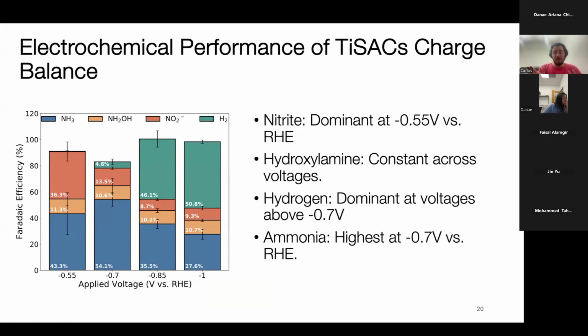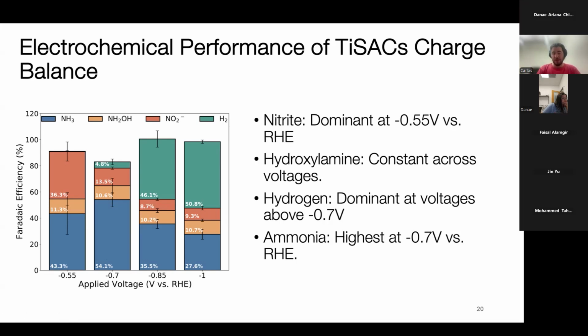So at very less negative potentials, so at 0.55, you can see that nitrite is the dominant species. Once you go around 0.7, the nitrite gets suppressed and you have a lot of ammonia as your predominant species. And after 0.7, so at 0.85 and -1, hydrogen starts becoming more active and you start seeing hydrogen as your predominant source of Faradaic efficiency. So the optimal performance for us to operate is negative 0.7 versus RHE. And any higher than that, you have a lot of competition versus hydrogen, and anything lower than that, nitrite is the predominant species.